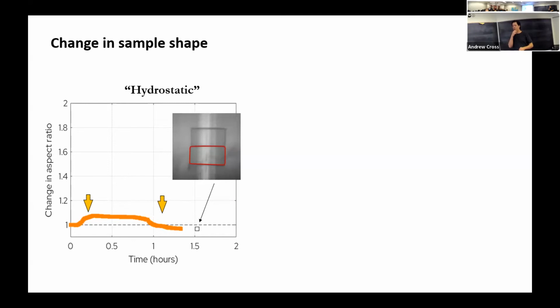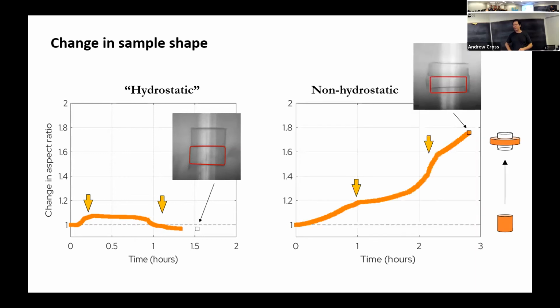So under our quote-unquote hydrostatic conditions, you get a small increase in the aspect ratio here, and that corresponds with sample flattening. But then crucially, once we go back from coesite into quartz, we get sample lengthening. So it ends up being the same shape that it was to begin with. So under perfectly hydrostatic conditions, like the little cartoon model that I showed earlier, we'd expect no real anisotropy in the volume change. We're seeing a small amount of anisotropy, a small amount of flattening.